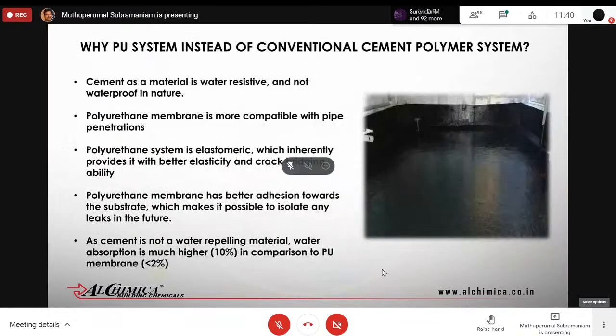Now, if you ask me why I should go for PU when there is a conventional cementitious waterproofing system, there are two important points which cannot be ignored. One is that the water absorption of cementitious coating is very high. It absorbs up to 10%, whereas polyurethane absorbs only 2%. This particular product absorbs 2%. And also, cementitious coating is a rigid system, so if there is any vibration in the structure due to construction activities, the cementitious coating cracks and fails, whereas polyurethane coating will stay, it can take the movement of the structure vibration.